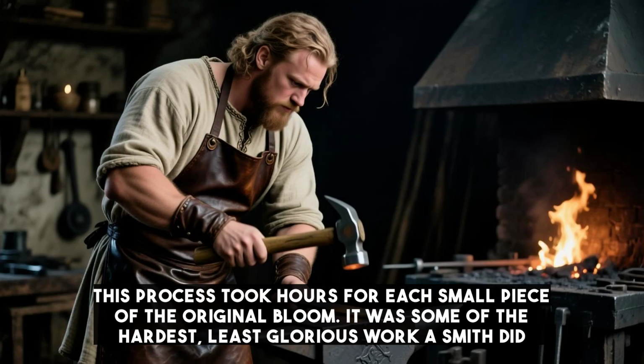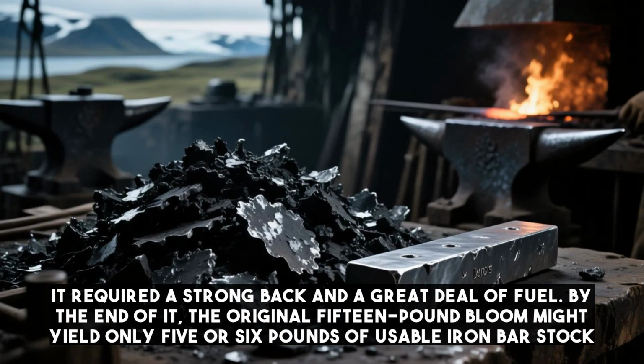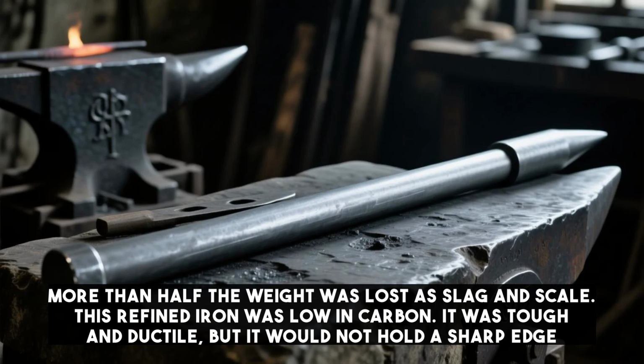This process took hours for each small piece of the original bloom. It was some of the hardest, least glorious work a smith did. It required a strong back and a great deal of fuel. By the end of it, the original 15-pound bloom might yield only 5 or 6 pounds of usable iron bar stock. More than half the weight was lost as slag and scale.